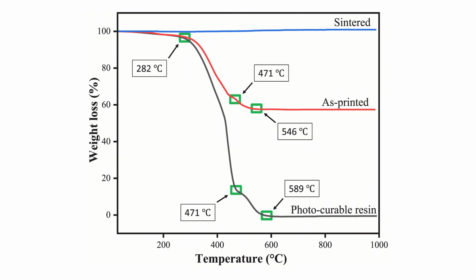We also ran something called thermal gravimetric analysis, or TGA. Basically, this shows how much weight is lost in the sample in relation to temperature. So it goes from 0 to 1,000 degrees Celsius. You can see that the sintered sample loses no weight, while the printed sample loses 40% of its weight because 40% of its weight was resin. So it proves that all the resin has been removed.